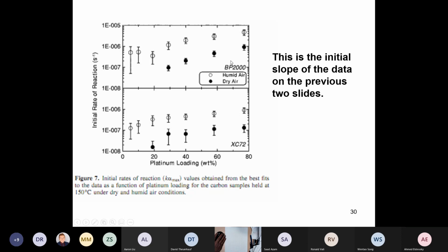And if you remember back to one of your earlier homeworks where you calculated the specific surface area of graphene, it's 2,600 meters squared per gram. So this Black Pearls 2000 is about as high a surface area as you can possibly get from a carbon black. And you can see that the degradation rates are much higher on the high surface area carbon than on the low surface area carbon. It's the same vertical scale on the two graphs.